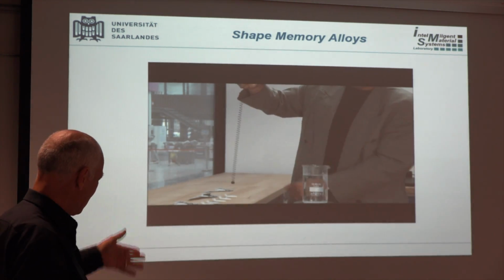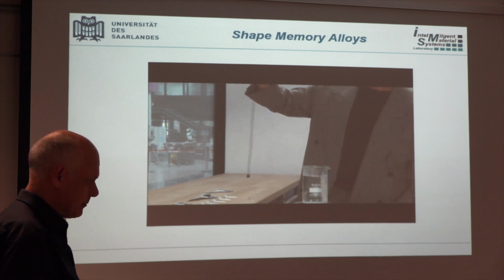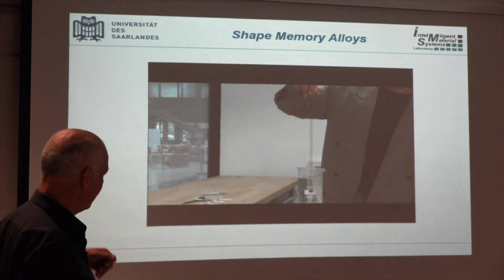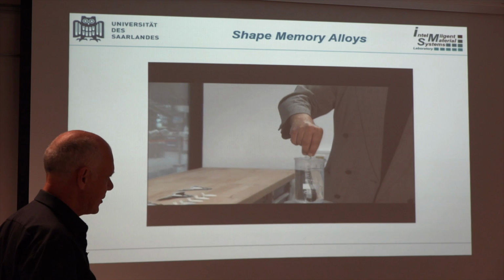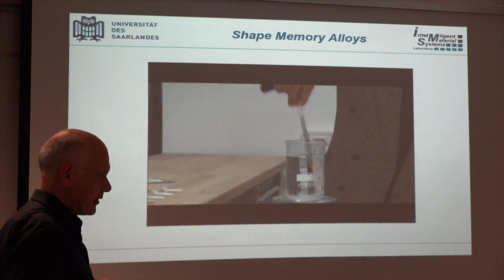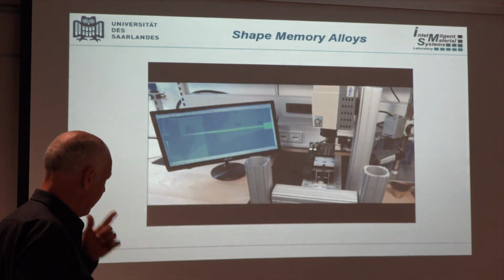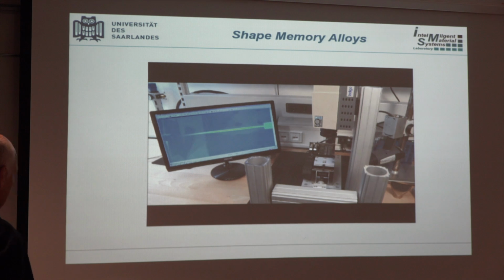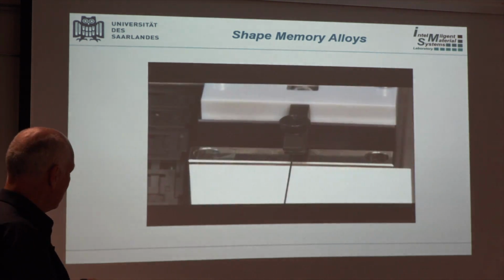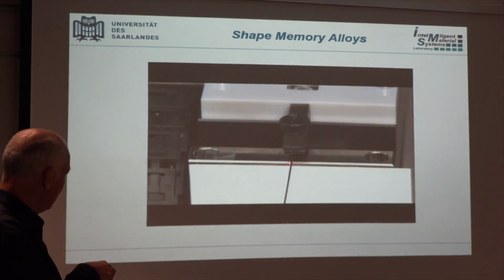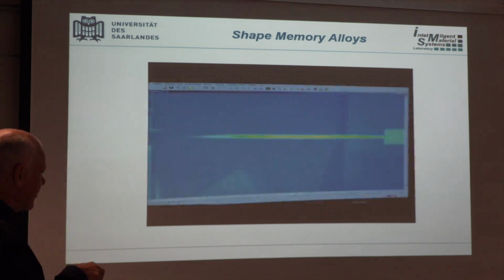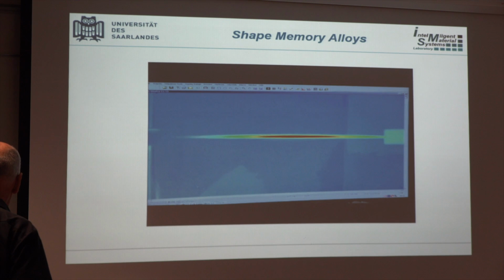So here's a spring that we made from nickel titanium, and you can stretch that largely, and I dip it in the water and see what happens. It just immediately remembers that it used to be a short and compact spring. So this is something that is very interesting. The other thing here is, we're pulling on this and we get all kinds of interesting temperature signals. I'll come back to that in a second.